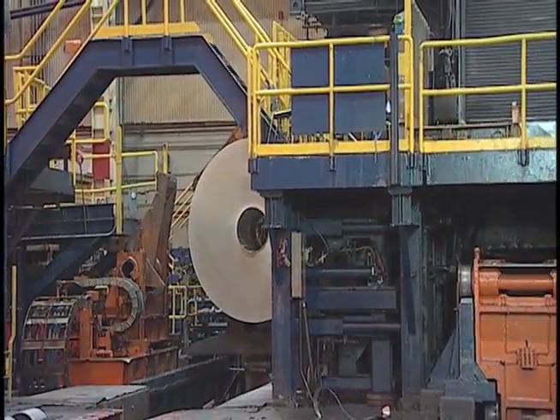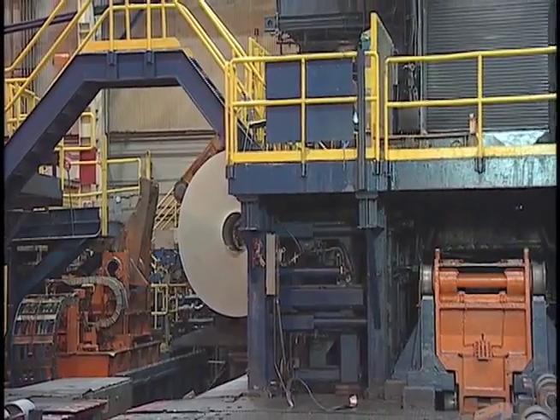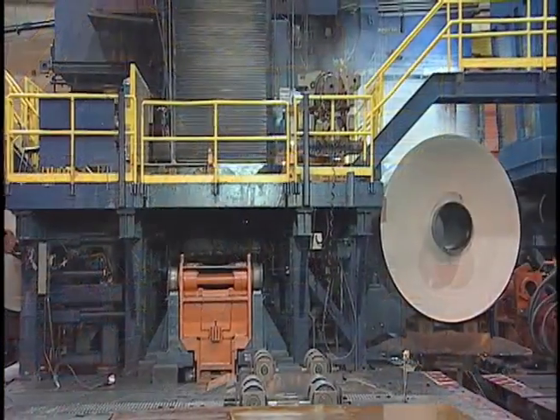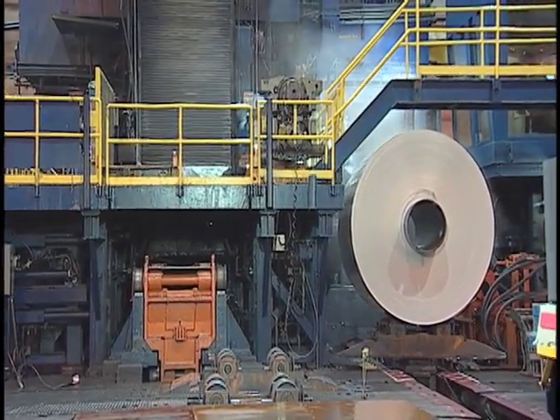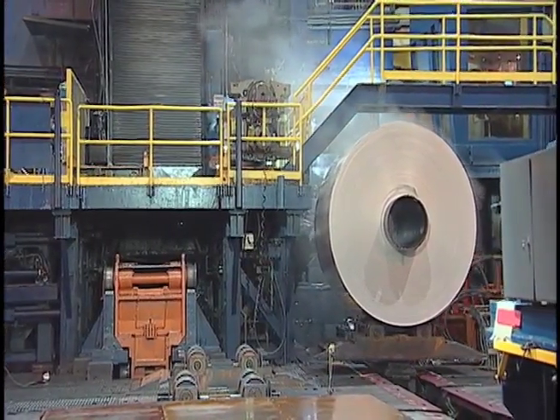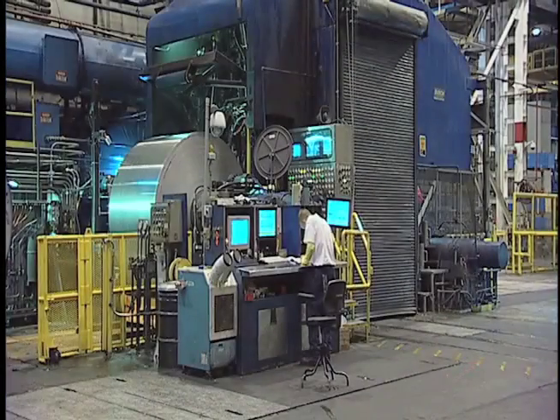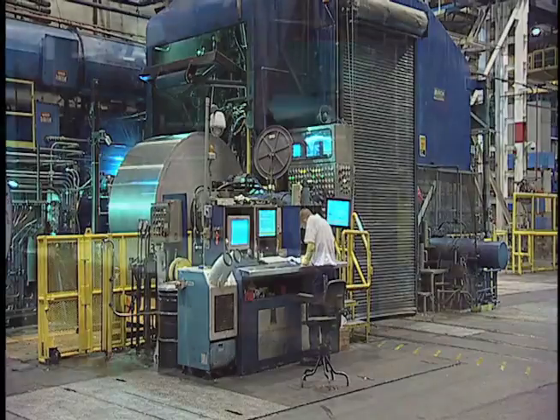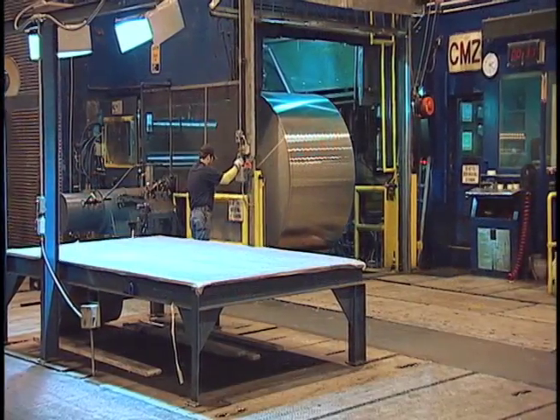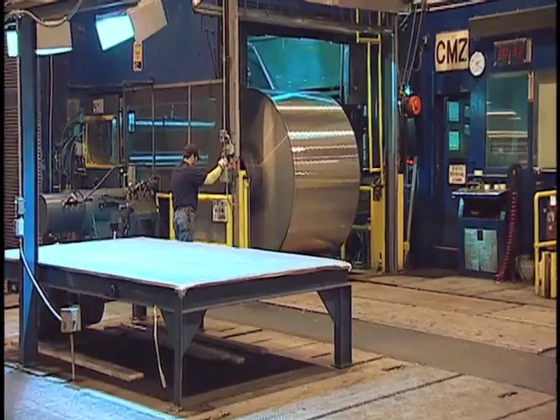The coil is then run through one of 3 cold mills in order to achieve the desired thickness or gauge of the sheet. This is achieved by the work and backup rolls applying tremendous pressure to the sheet. The sheet is recoiled onto a metal sleeve. By running the coils through a variety of paths, the sheet can be taken from a thickness of 1/10 of an inch to the thickness of a piece of paper.